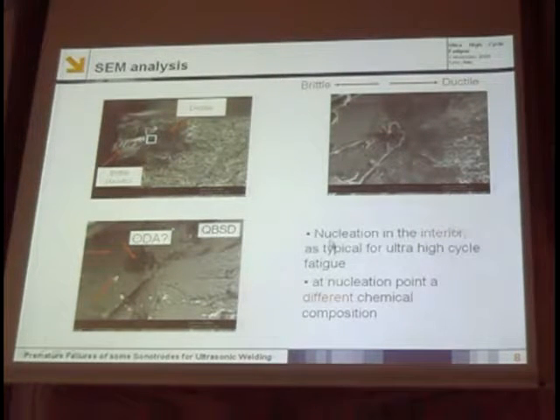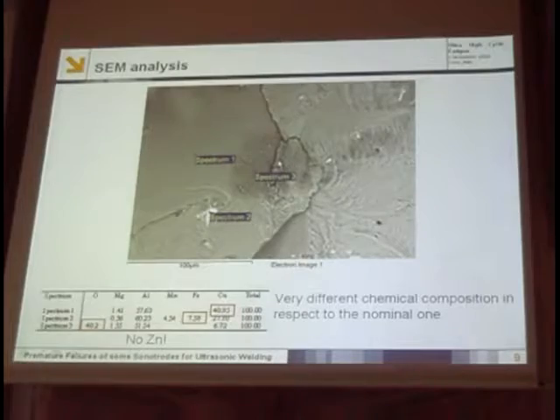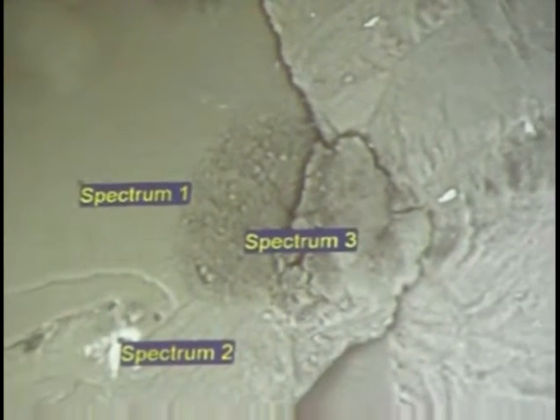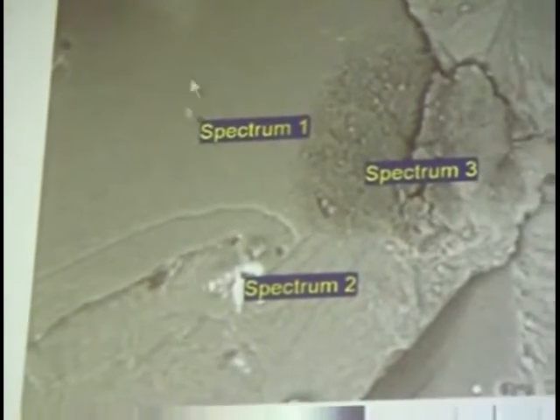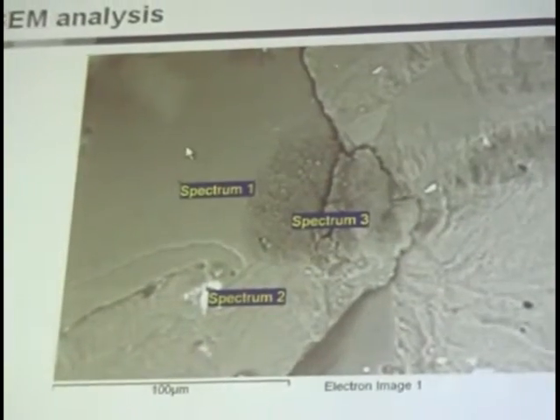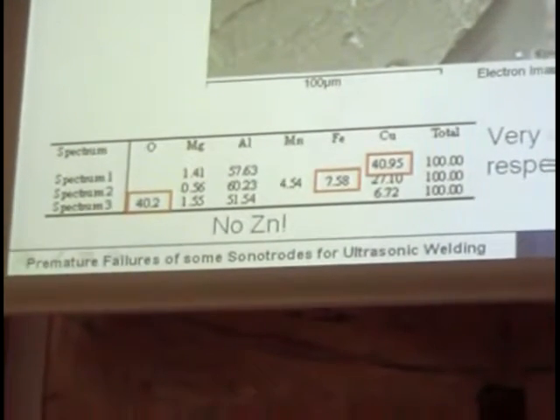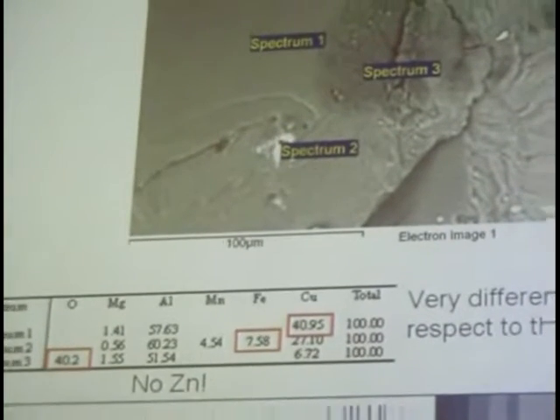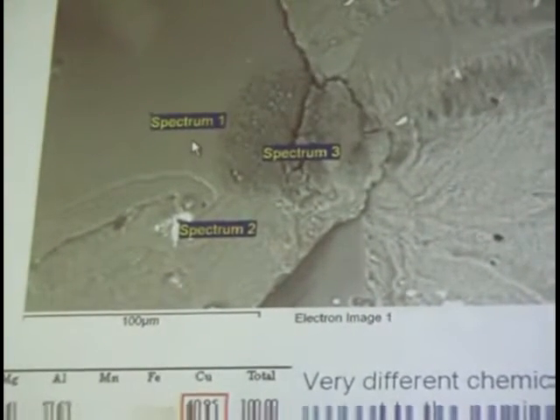But what is really important is that the nucleation for this kind is obviously in the interior, as we expect for very high cycle fatigue. And the nucleation point, as we will see on this other side, is very different from the one expected for the 7075 alloy. Particularly, we see that spectrum 1 is this part that I told you to remember, because in this part we have a huge amount of copper. Really a huge amount, 40% around here. While here, this white particle is an iron particle, because we have a quite high percentage with respect to what is expected from the ASTM specification for this alloy.